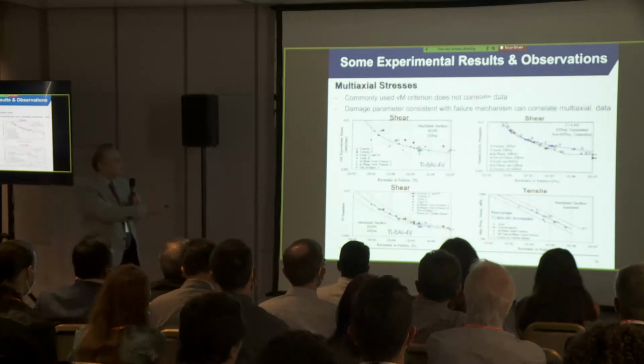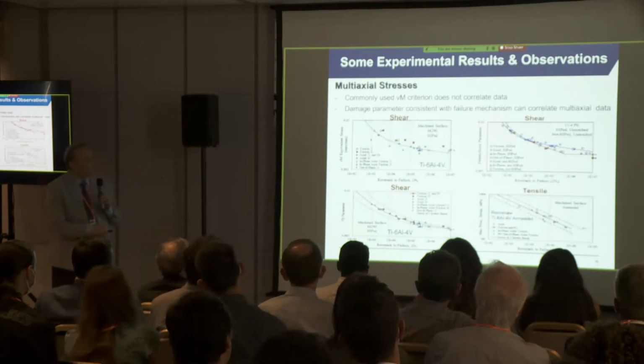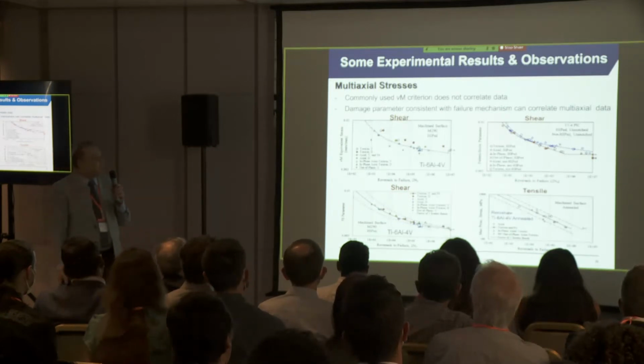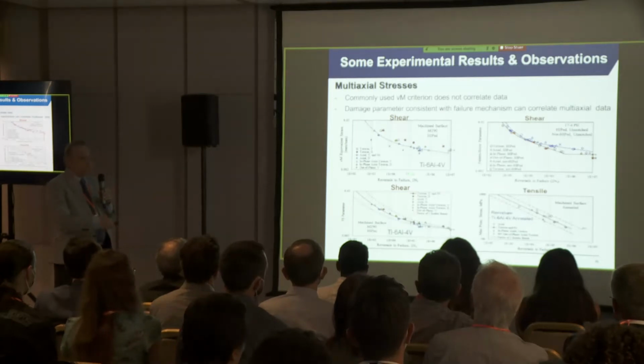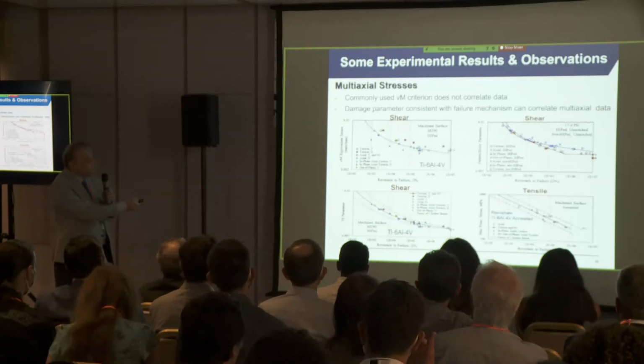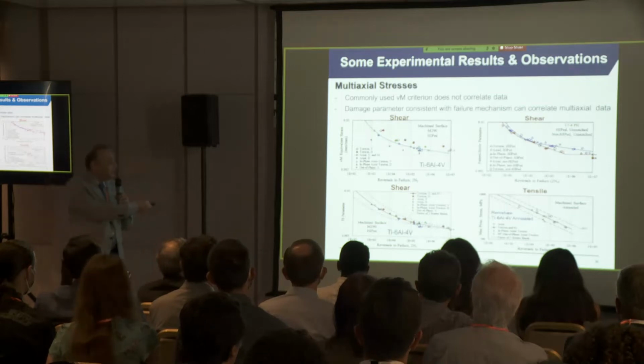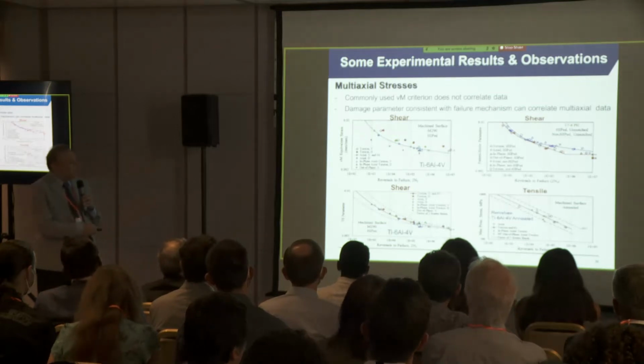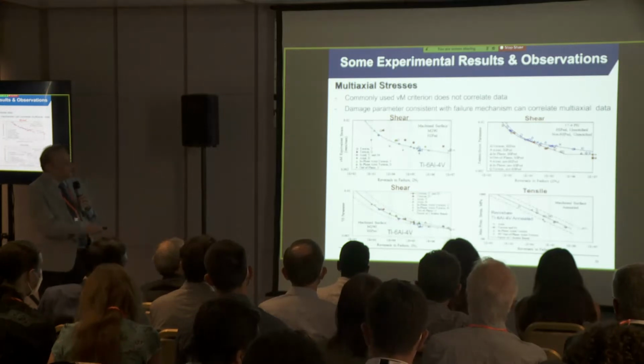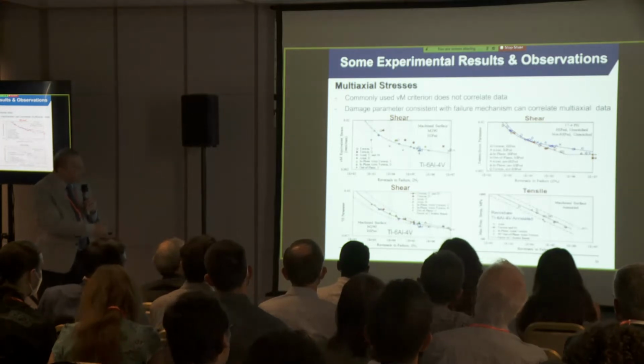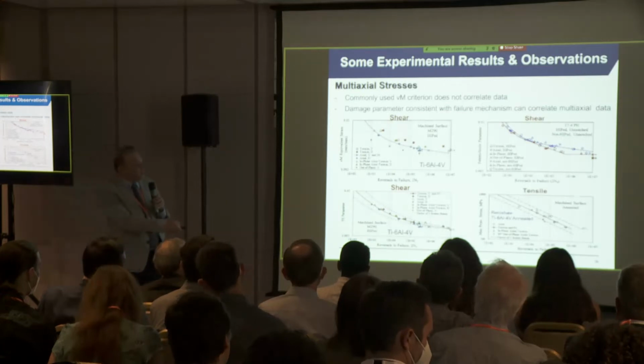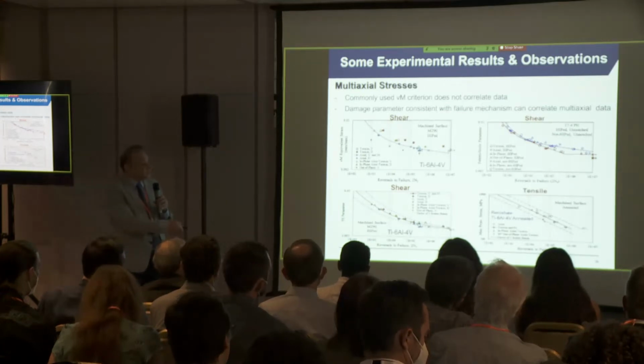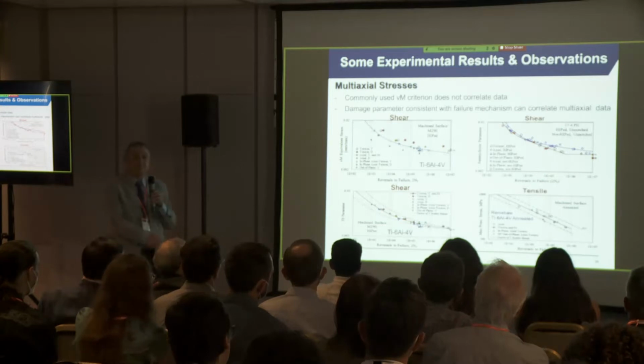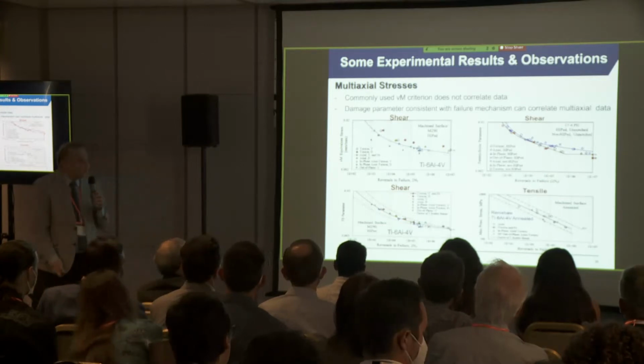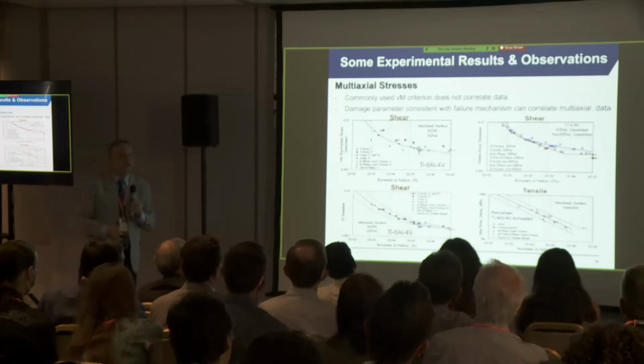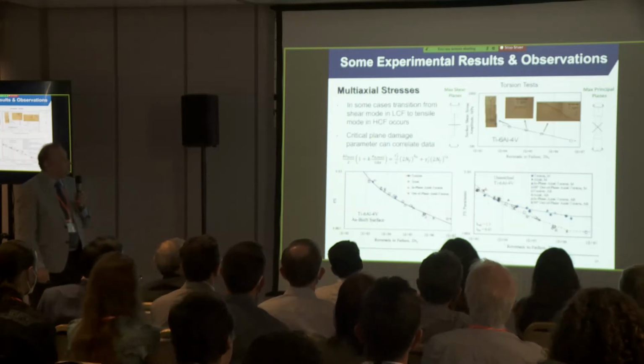Okay, so these are some fatigue data under axial loading, torsion loading, and combined axial-torsion loading. Typically, we use von Mises when we have combined loads, so you can see the data are not correlated very well. If you use the critical plane approach, you can see the data very nicely come together. If it's a shear mechanism, you can use a critical plane approach which is based on shear. If it is a tensile damage mechanism, you can use a critical plane damage parameter which is based on maximum principal stress, for example. So damage mechanism consideration is an important factor.